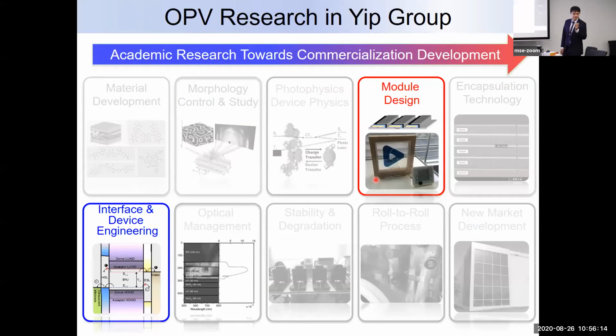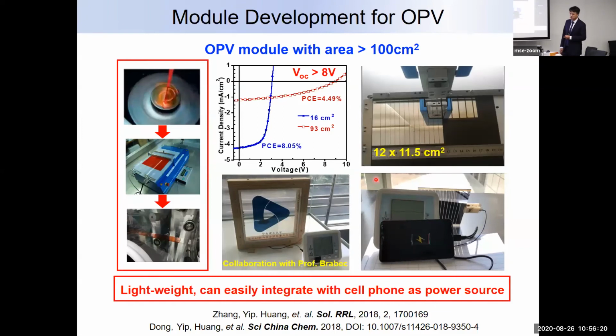So the last two slides are talking about module design, and we are also working on the translation from the laboratory. We are always doing this spin coating, but this cannot be applied for large-scale fabrication. So therefore, we also work on blade coating, optimizing the film formation properties, and also roll-to-roll printing. And you can see now we can make a larger module. This is one demonstration: when you put this module under the sun, you can charge up the iPhone. So eventually, this area is close to the surface area of the iPhone, and this can also be a flexible film, so you can even integrate it into the cover of your cell phone.